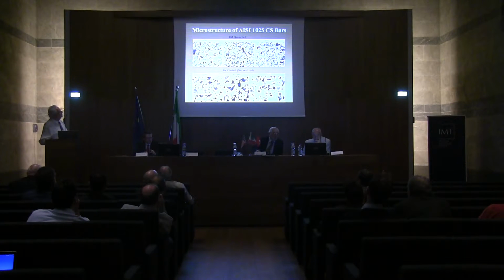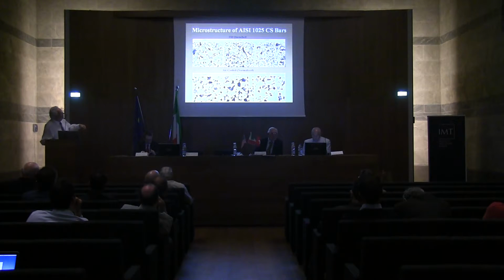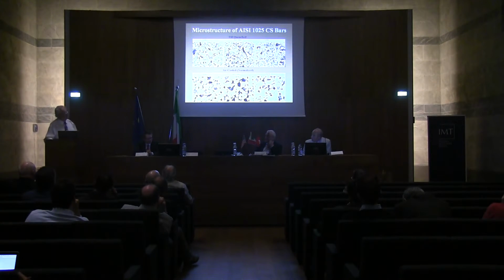Here are examples of the microstructures. On the top is oil quenched, on the bottom is the air-cooled or normalized condition. The left picture in both cases is the surface microstructure, the middle is the mid-radius, and the right-hand side is the center. These are all at 500x, etched with nital. You can see we have nothing but ferrite and pearlite. In the upper left at the surface, we've got a little bit of bainite, but otherwise, in the normalized condition, it's all ferrite and pearlite. There is some bainite in the mid-radius location for the oil quenched, but not much in the center.